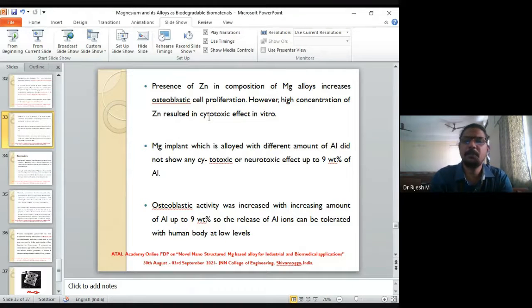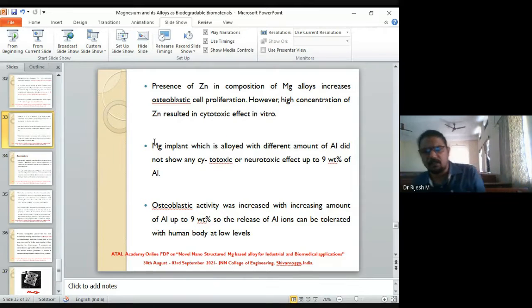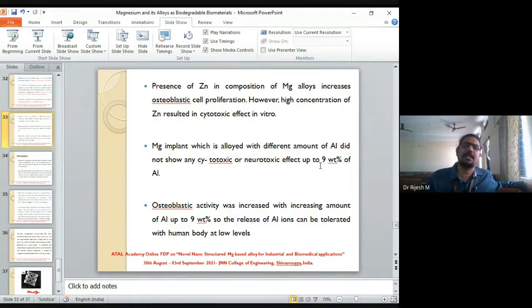Magnesium implants alloyed with different amounts of aluminum surprisingly did not show any cytotoxic or neurotoxic effects, up to 9%. Magnesium aluminum is a very common alloy, generally not recommended in many biomaterials. One of the reasons is that aluminum has a neurotoxic effect after a certain time, but it has been proved that up to 9% it is not cytotoxic or neurotoxic. But if the aluminum content is more than 9%, you need to worry. So magnesium aluminum works well if the aluminum content is less than 9%.